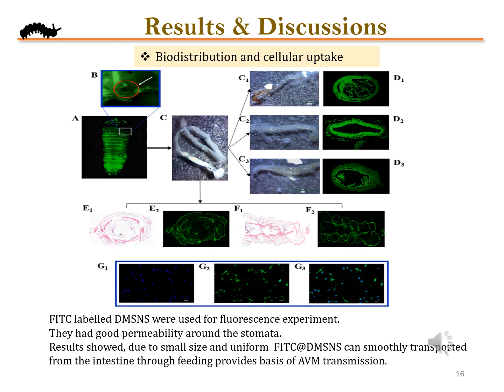Biodistribution and cellular uptake test is a fluorescent experiment performed to check the transmission of the drug material into the epidermis as well as the stomata, and it showed good results due to the small size and uniformity, and concluded that FITC loaded DMSNs smoothly transported through the intestine through feeding on the basis of AVM transmission.